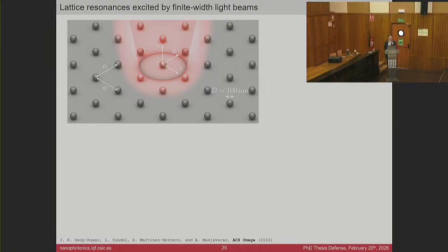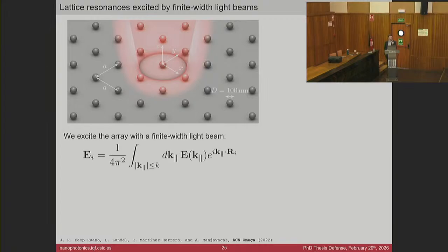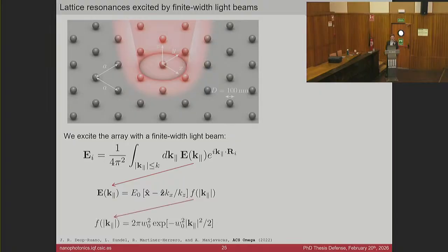So to analyze this, I model my electric field by means of this Fourier transform, which you can understand just as a sum over plane waves with a certain amplitude. And I define this beam, which is mainly polarized in the x direction and has a Gaussian envelope. And very importantly, we are going to control the size of this beam in real space by means of this W0 parameter that you can understand as the beam width.